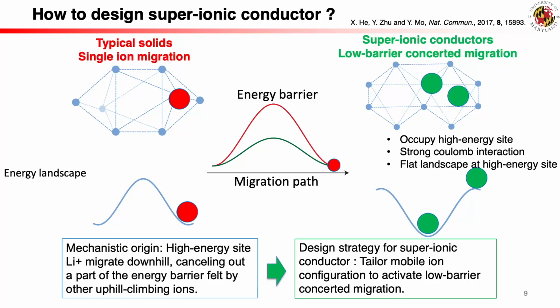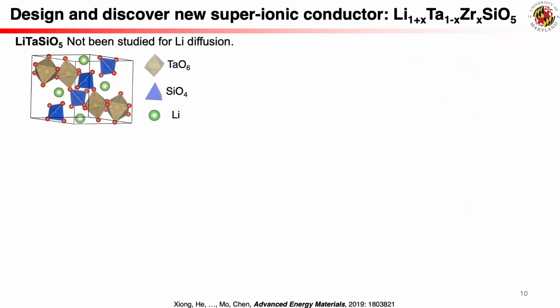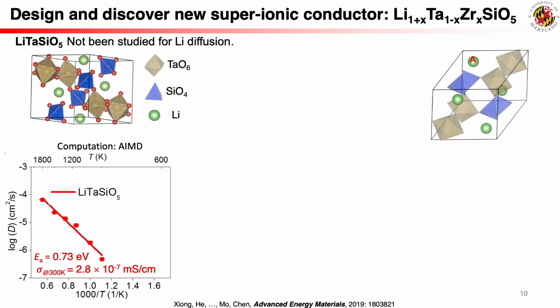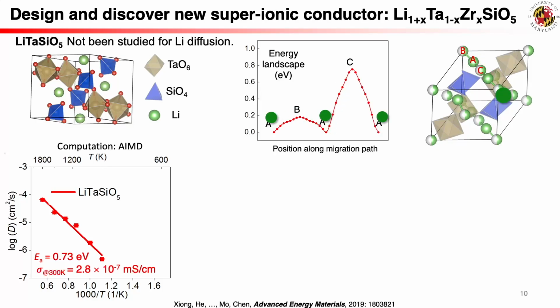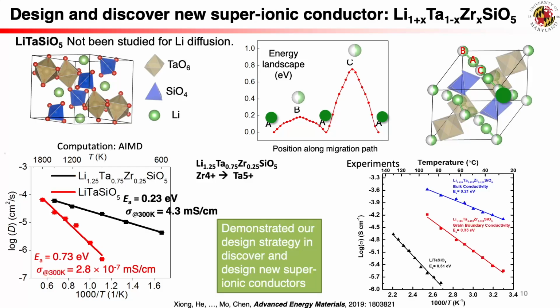And they actually tested this design idea in simulations, right? Yeah, they designed two new potential SICs. What were they? LiTaSiO5 and Li1.25Ta0.75Zr0.25SiO5. Okay. And they doped these materials to introduce extra lithium ions into those high-energy sites. Exactly. And what happened? They saw significantly reduced migration barriers. Okay. And what about conductivity? They predicted conductivities comparable to known SICs. Wow, so it really works. It's a proof of concept.